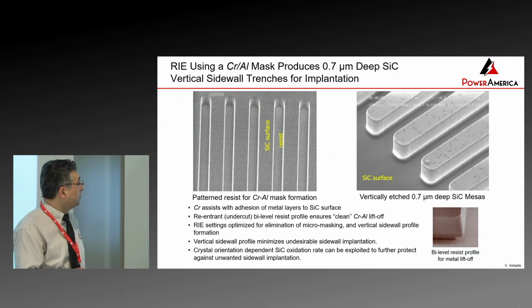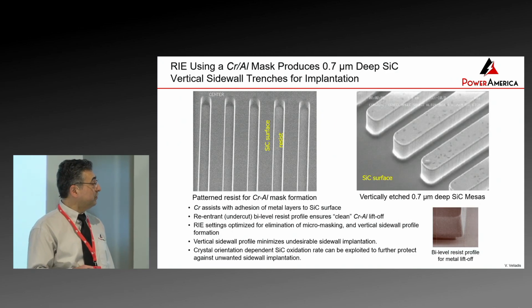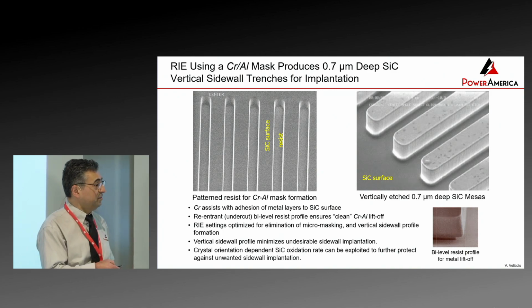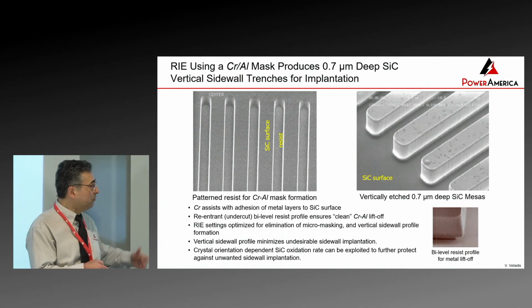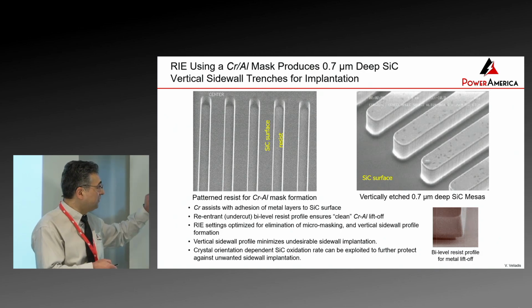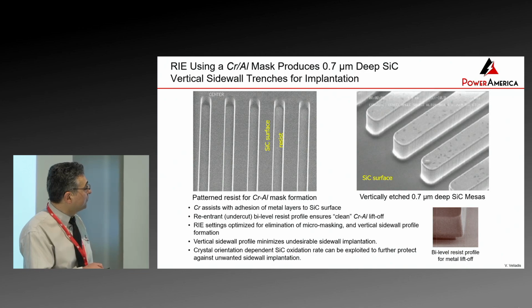But you play long enough with the tool and the mask and the chrome, aluminum deposition. Chrome is basically for adhesion. You don't want to put aluminum directly on silicon carbide. And you can see these are nice vertical sidewalls, 0.7 micron, very clean.